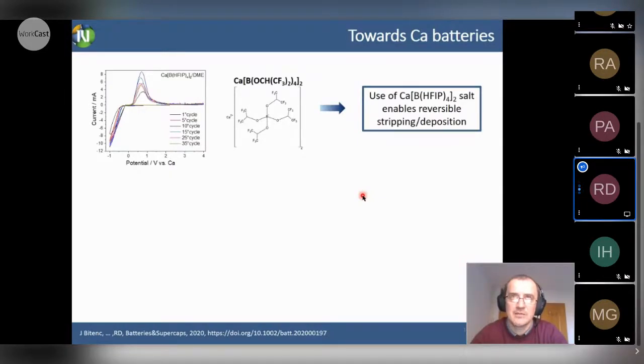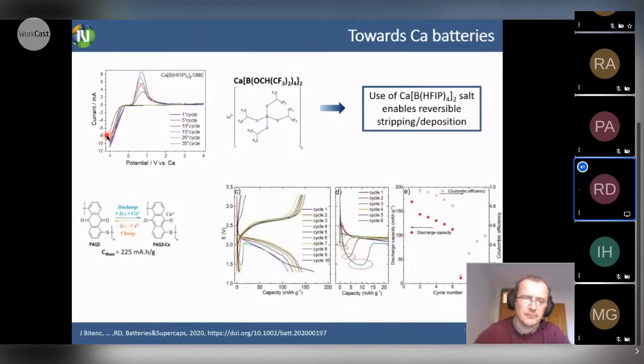So in calcium batteries for the room temperature stripping and deposition process, we are again using this boron hexafluoroisopropoxide salt, in this case the calcium analog, and you can see here we can have a nice reversible stripping and deposition at room temperature. But when we put this into the battery, again, here is anthraquinone. This time PAQ is linked with the sulfur. When we put this into the battery, we can obtain several very nice cycles, with some capacity fading. But then we observe a sudden capacity drop.